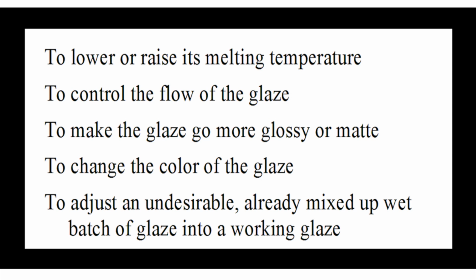For example, to control the flow of a glossy glaze, one can adjust the clay amount, or you can adjust the silica amount. Both will affect the flow of the glaze, but in different ways. The following tests will show results which you can then choose—which stripe you like best—and then mix up that recipe.